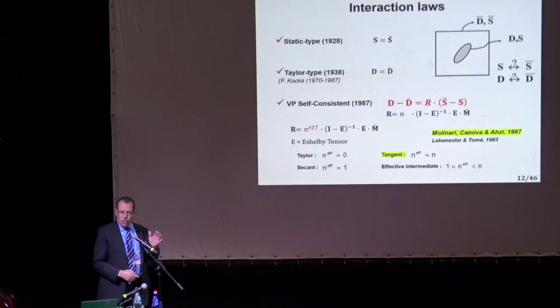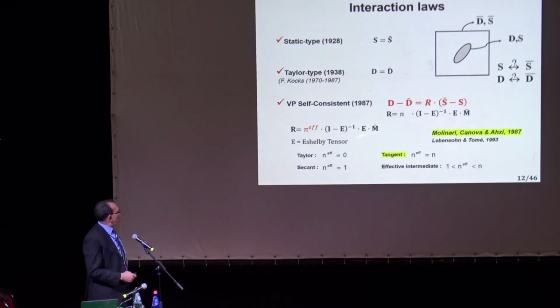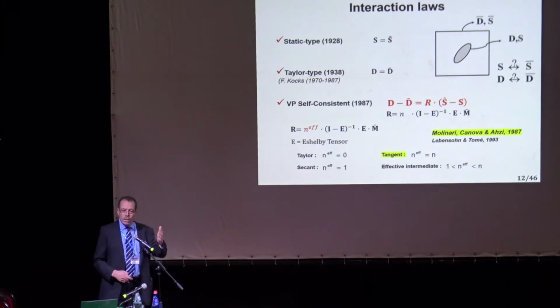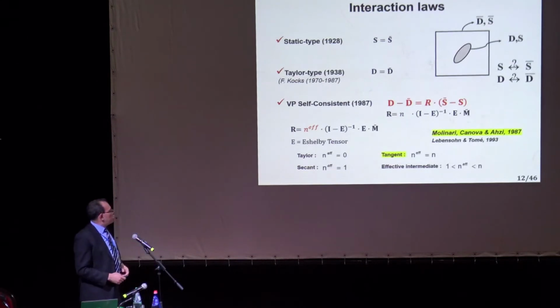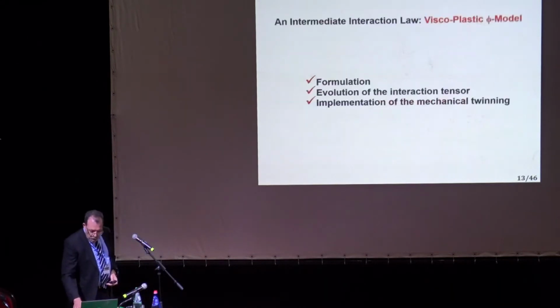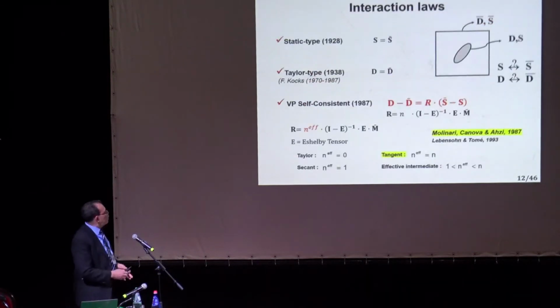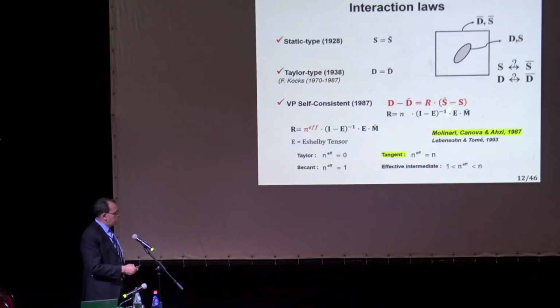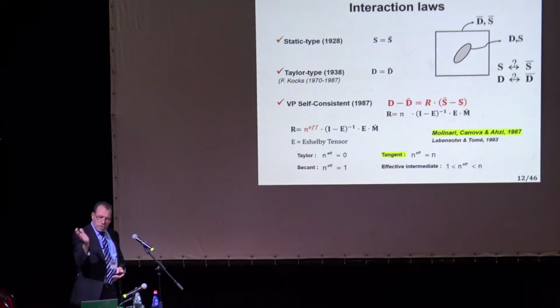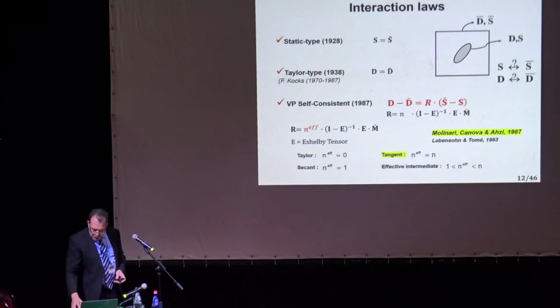We knew what the problem was from the beginning. And then we could also generalize it. If we put an N effective equal to 0, then you have the upper bound, what we call in plasticity the Taylor model. But that's the upper bound solution, okay? So now, with this model, you have to deal with the Eshelby tensor. You have to calculate an Eshelby tensor for each time step, for each single crystal, especially if you have ellipsoids that are oriented in different directions and so on.